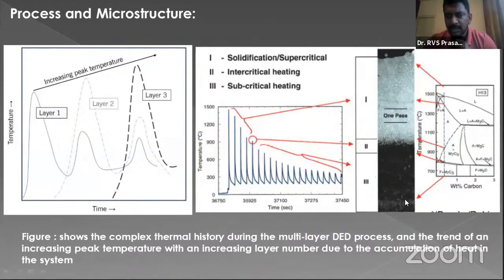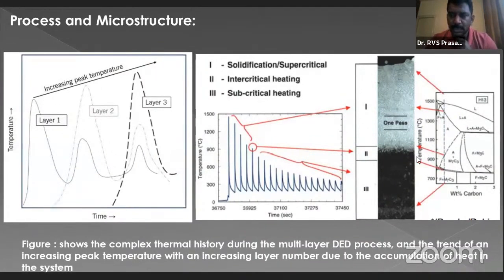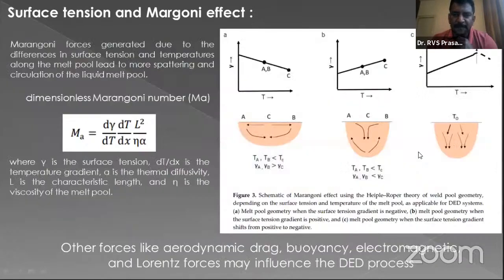It's very important. Once you finish this process, heat treatment is a very important aspect with respect to direct energy deposition. Also, in direct energy deposition, the melt pool dynamics are very important. For example, if you consider the surface tension and the Marangoni effect, which is very critical.